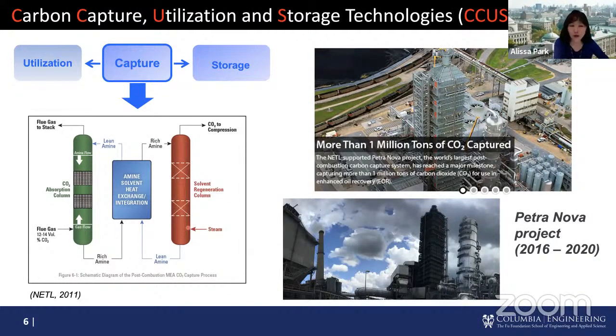And that's why we've been working quite a bit on amine functional groups, because amine is pretty good at capturing CO2, but also not too strong, so that a minimum, optimized, moderate energy requirement is needed to regenerate this solvent, which is about 120 to 140 degrees C of heat we can provide. So looking at all these, we learned so much about how fast this reaction kinetic is and how selective this material is. And it's very easy to move this liquid solvent around, pumping it and designing reactors. So there are a lot of benefits.